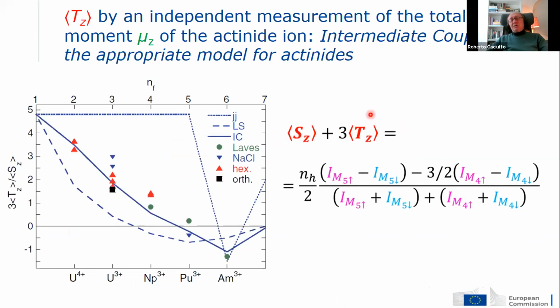A problem is the determination of this operator, this magnetic dipole TZ. Well, for several compounds, this quantity is known from independent measurements, for instance neutron diffraction, or in the case of neptunium compounds from Mossbauer spectroscopy. Trying to build a systematic in this case led to the discovery that the ratio between TZ and SZ is essentially well described by intermediate coupling approximation models. Not JJ, not Russell-Saunders, but intermediate coupling. Then when you cannot use independent information to estimate TZ from experiment, you can calculate this in intermediate coupling approximation and then determine the other two quantities.